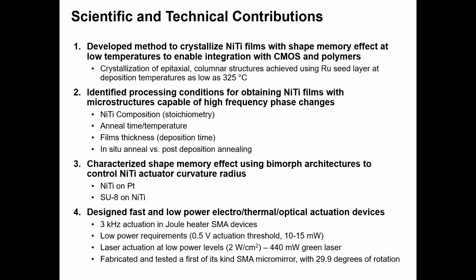So I would say here, the heart and soul of any successful PhD is no doubt these scientific and technical contributions. So here I lay out the 4 main contributions enabled by this body of work. First and foremost is that I developed methods to crystallize nanoscale thickness SMA films with shape memory effects at lowered processing temperatures to enable integration with CMOS and polymers. The second main contribution was identifying the processing conditions for obtaining NiTi films with microstructures capable of high frequency phase changes. This was done by careful examination of the shape memory properties and how they are impacted by a variety of the processing conditions listed here.